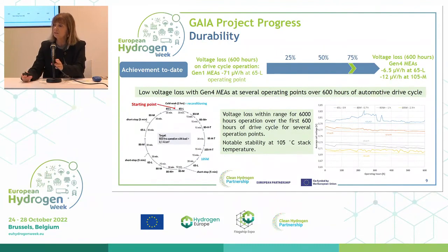In terms of the durability, these 4th generation MEAs were tested according to an automotive drive cycle that included these different operation points for certain durations at certain temperatures. I'm not sure how clear this one is here, but it's showing you the degradation rate over the first 600 operating hours, including at high temperature at the 105 degrees operating point. And the voltage loss is within the range for ultimately a 6,000 hour operation over those first 600 hours of operation. So once again, we've moved forward and made a lot of progress in terms of durability with these Gen 4 MEAs integrating new materials.